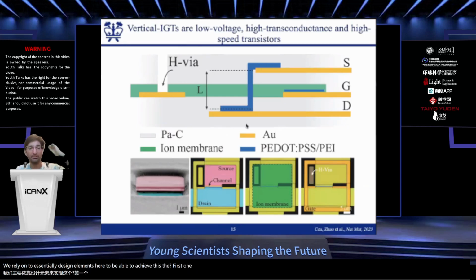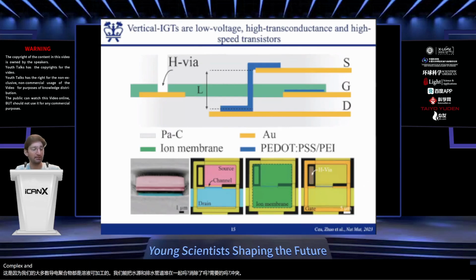The first one was utilization of a vertical transistor channel. This is because the majority of our conducting polymers are solution processable. We're able to stack the source and drain together, eliminate the need for complex and slow processes of ion beam lithography, and create channels that are vertical. We also were able to completely encapsulate the device, but provide hydration through a vertical access point. We call it the H-via, hydration via, where it allows water to hydrate the channel and mobilize its self-sufficient ions.